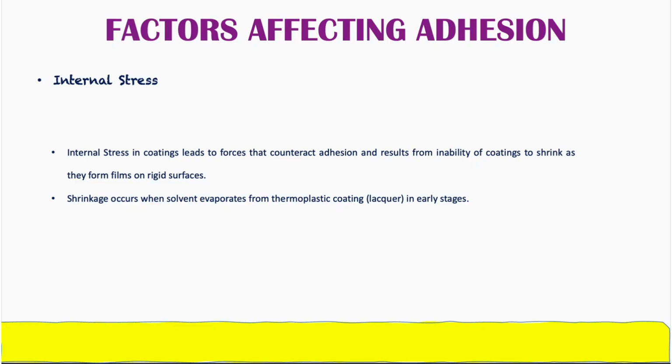Let's say we apply some UV cured polymeric coatings, specifically acrylated resins, and the mechanism of polymerization followed here is free radical polymerization. When the polymerization onsets, the polymeric chains link together, and that process takes only a fraction of a second at room temperature. If the rate of polymerization is high, the shrinkage will happen at a faster pace. So large shrinkage accompanies the polymerization of the double bonds, which leads to poor adhesion properties of the coating, because the polymer is not getting the time for relaxation.